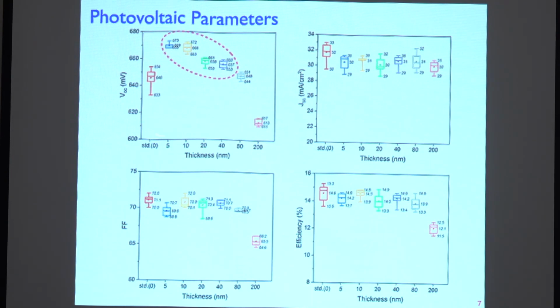This graph on the upper left here is the value of the open circuit voltage. The standard device has a VOC average of about 640 millivolt. But when we put 135 at a thickness of 5, 10, 20, or 40 nanometer on top of 112, we can see a significant increase in the open circuit voltage. However, the current of this device with the 135 capping layer decreased a little bit. When we look at the efficiency of the device with 135 on top of 112, it's comparable to 112. However, the open circuit voltage was significantly increased.